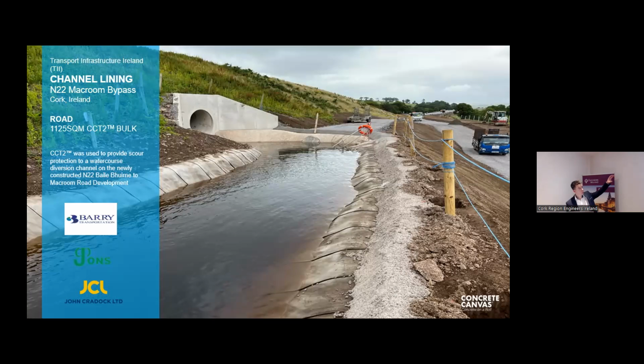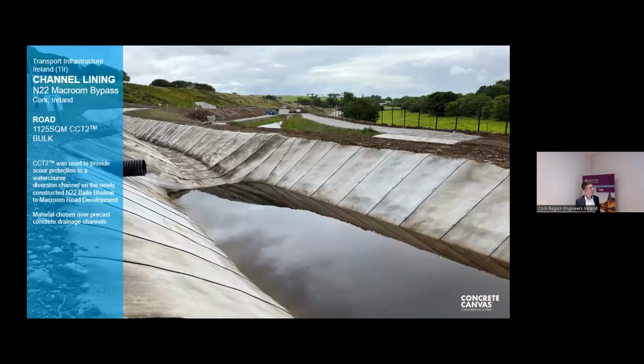So the water is running through the culvert underneath the newly constructed dual carriageway into the stilling basin, then it flows downstream for 150 linear meters. So just over 1,100 square meters of Type 2 GCCM was installed. And you notice here, as I mentioned earlier, that non-erodible fill was Class 1 material on the left-hand side, but on the right-hand side, they used poured concrete because there was a risk of water getting underneath on that side. So just keep in mind, depending on the erosion requirements, we may recommend poured concrete or just Class 1 material for the anchor trenching. And that's the final photograph from the N22 scheme.